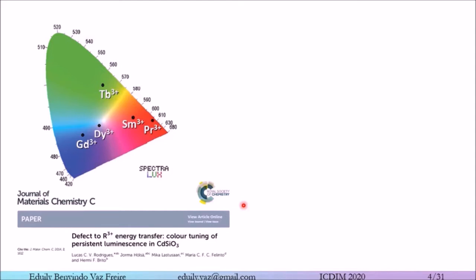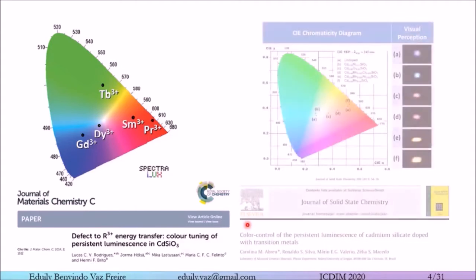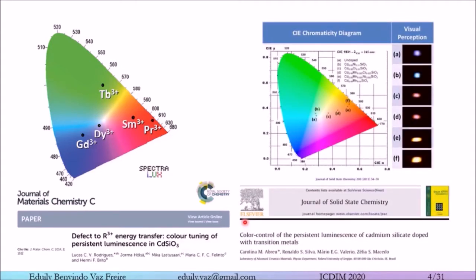That is, luminescence in different colors using only the matrix CdSiO3 for this purpose. Here you can see in this paper cadmium silicate doped with dysprosium, gadolinium, terbium, samarium, and praseodymium. And we identified the different colors of luminescence depending only on the doping ion. We can see that these colors can be from violet to red, even close to white when doped with dysprosium.